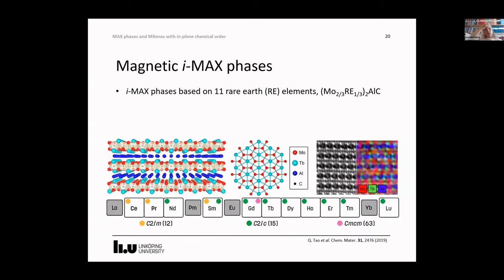Since we've been working quite a lot on magnetic MAX phases in the past, we were eager to explore if we could incorporate magnetic elements into IMAX phases and to explore the magnetic properties. So we worked on rare earth-based IMAX of this formula. Here you see the lanthanides that we used, 11 of them, and a schematic image of one of them. It's moly-terbium aluminium carbide, also shown here in the STEM with atomically resolved EDX.